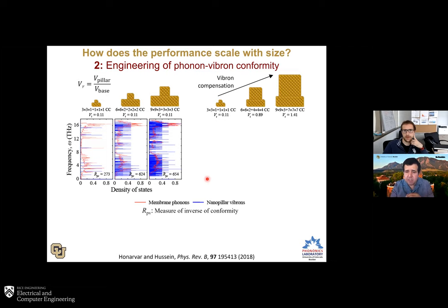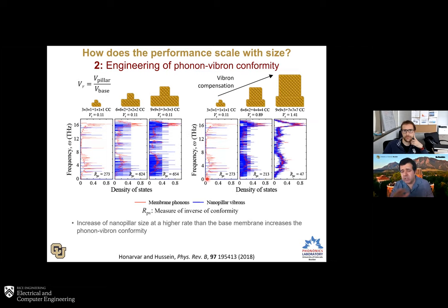If we do that, we found the result to be quite remarkable. We found that, in fact, the two density of states match perfectly at some point once we grow the pillar size compared to the membrane enough. And that opened up the opportunity that we can scale up while also optimizing the performance. So this was a really important milestone for this research.